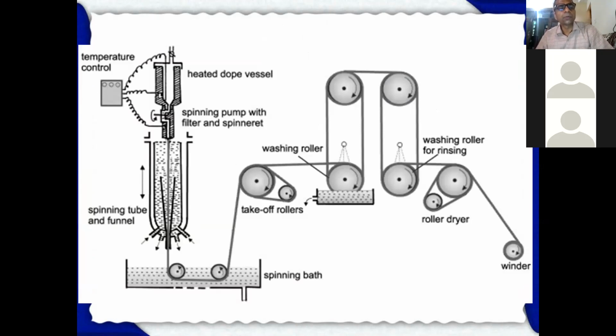This is a flow sheet, you can see, the commercial setup for Kevlar fiber manufacturing, where a temperature control unit is there, a heated dope vessel is there, and here you can feed 1 ton to 2 ton of this fiber manufacturing solution, where the solid content will remain around 10%. With the help of this spinning pump, this fiber forming solution will extrude to the spinning bath with an air gap of 3 to 5 mm. After coagulation, after solidification, the fiber will come in a spinning bath where the remaining solidification will take place.